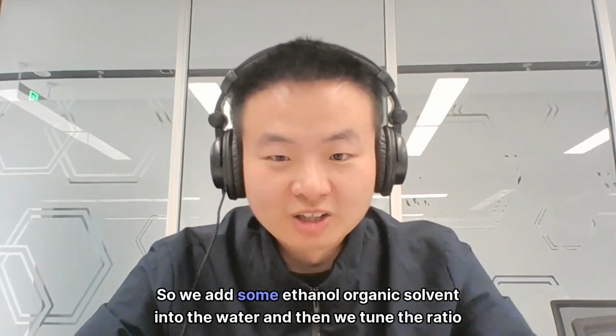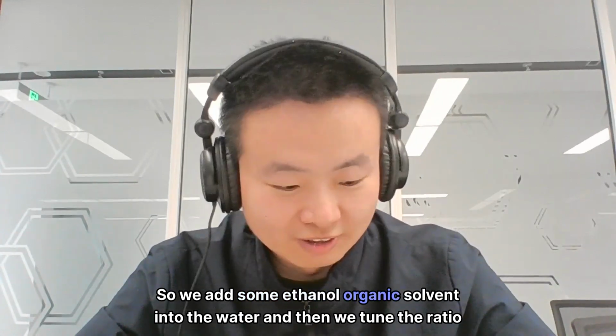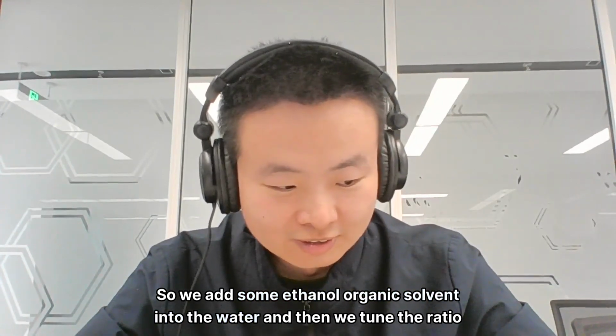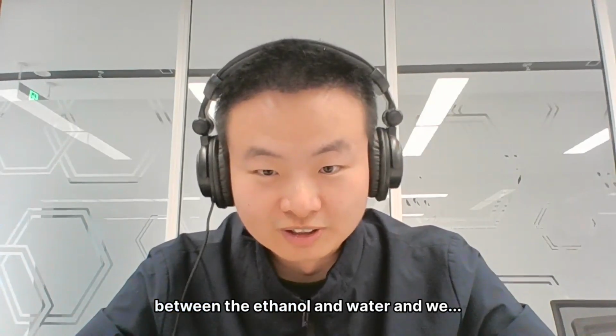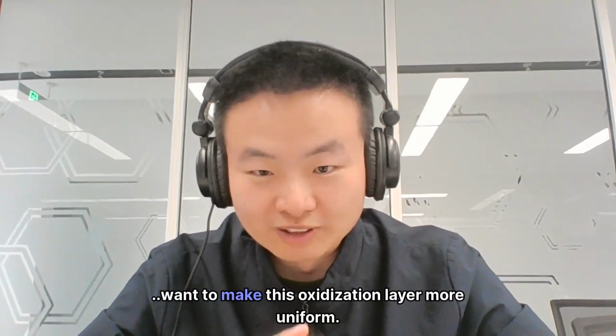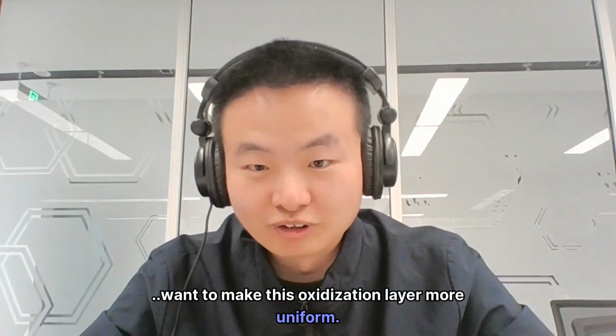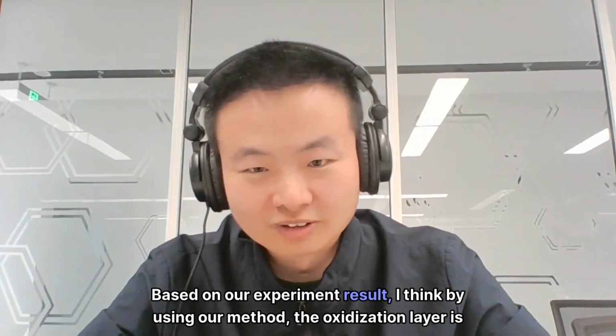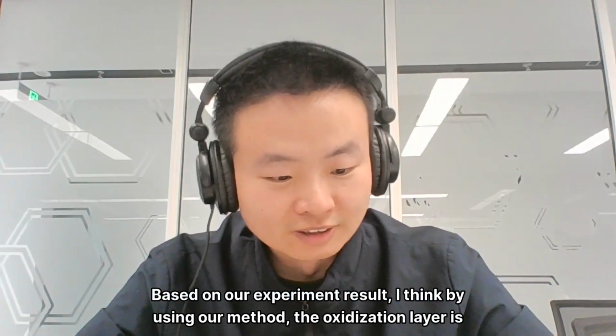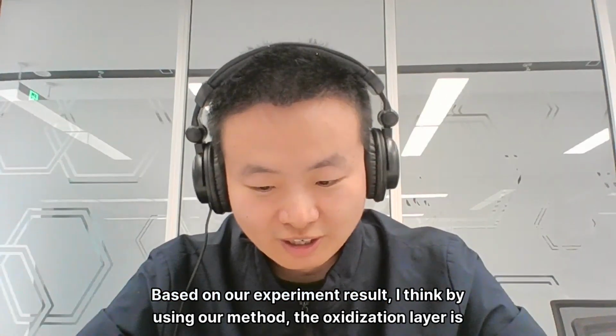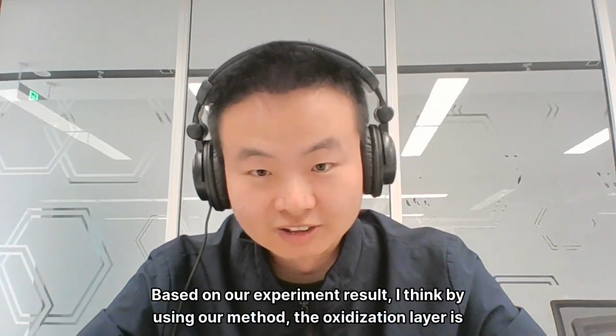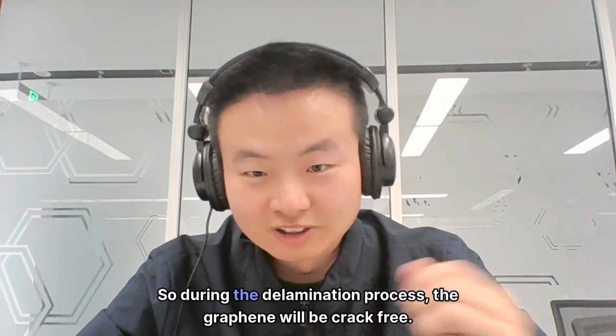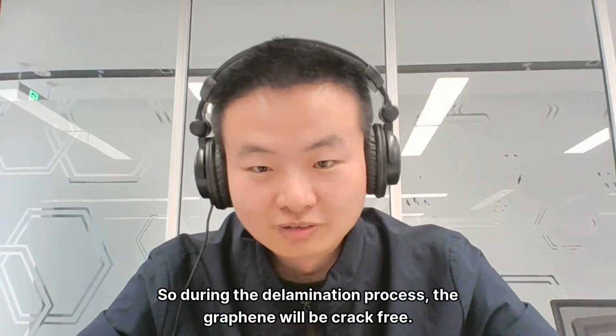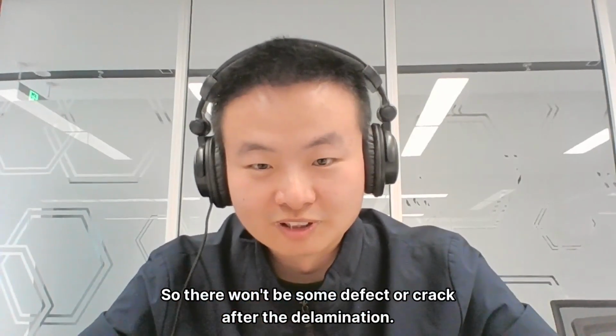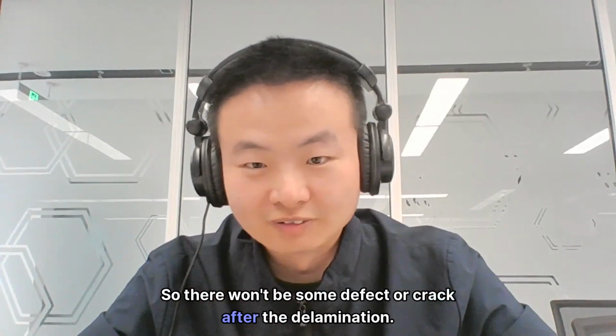So we add some ethanol, the organic solvent, into the water, and then we tune the ratio between the ethanol and water, and we want to make this oxidation layer more uniform. So that's what we do. And based on our experiment result, by using our method, the oxidation layer is quite uniform now. So during the delamination process, the graphene will be crack-free, so there won't be some defect or crack after the delamination.